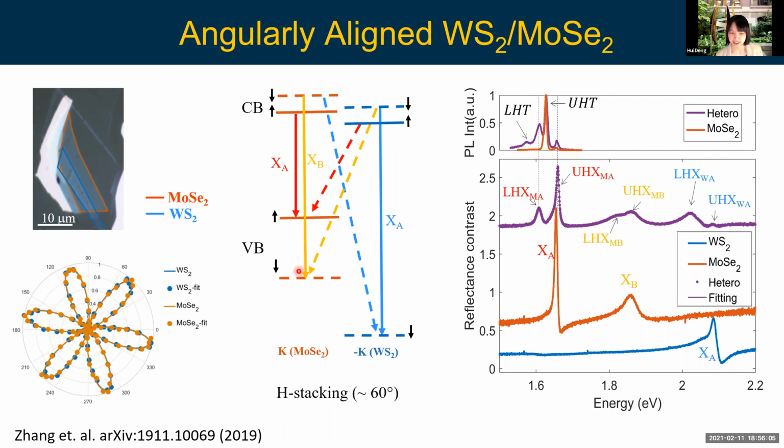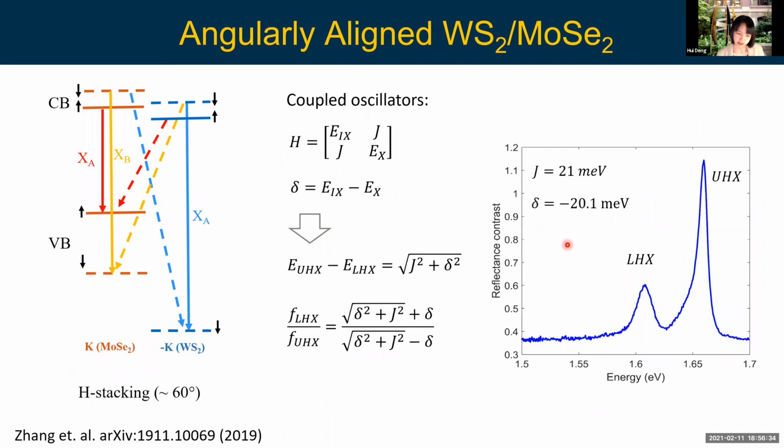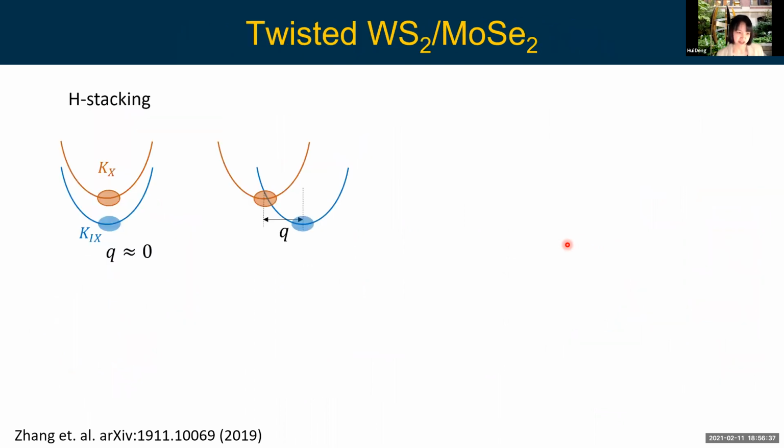Once they hybridize because of electron tunneling, they share the coupling strengths from that transition. So the absorption strength from this one now gets split into these two coupled resonances. That's how we can see these coupled resonances. And that also gives us a way to know we have such a hybridization going on in the system, and we can use that to deduce the tunneling strengths, et cetera.